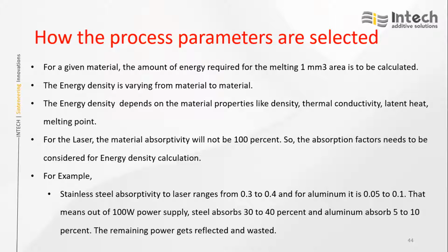But there are a lot of losses when laser interacts with the material, so all those losses also we need to consider. For example, stainless steel absorptivity to laser is 0.3 to 0.4, meaning 60 to 70% of the input energy for stainless steel is wasted; only 30% is taken. So whatever energy density you calculated, for a given power, only 30% is useful. If you give 100 watts, only 30 watts is useful. So if the requirement is 150 watts, you have to use almost 500 watts.